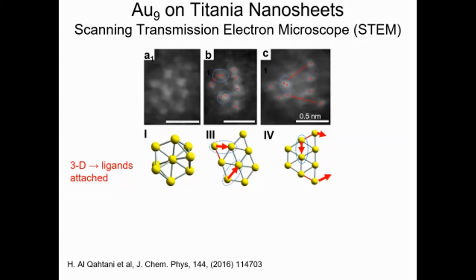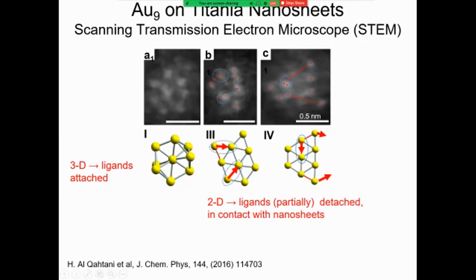And we classified them into 3 categories. The first category, as you saw here, what you see now, the white spot is just a single atom itself. The scale bar here is 0.5 nanometer, which is related to the gold core of our nanocluster. We saw them in 3D at the beginning. Then, when some of the ligands are removed because of the attachment to the nanosheet and because of the electron beam, we saw a 2-dimensional form of this nanocluster. This will help us understand the structure and what our gold 9 cluster looks like when it is deposited on the nanosheet.